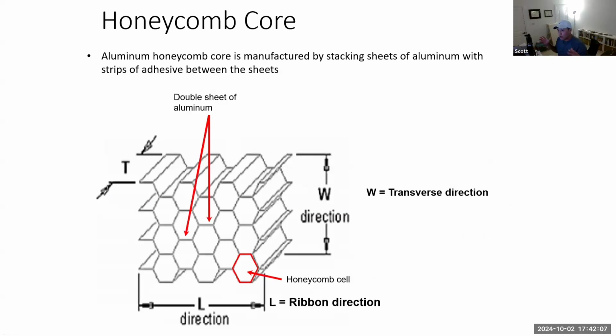So we went over the carbon fiber forms. Now let's go over the core, which is typically aluminum, but I also mentioned Nomex. It's manufactured by stacking sheets of aluminum with strips of adhesive between the sheets. So in a certain direction, that's where the two sheets are interfacing, and that direction is called the ribbon direction. That's this direction here. And then the perpendicular direction is considered the transverse direction. The stiffness and strength are different between the two directions because the sheets are bonded only in the ribbon direction. So typically the ribbon direction will have higher stiffness and higher strength relative to the transverse. And then this is the honeycomb cell.